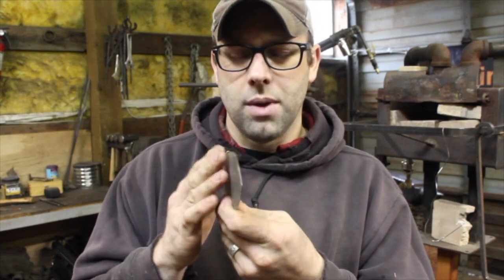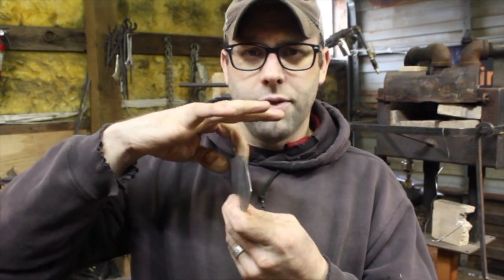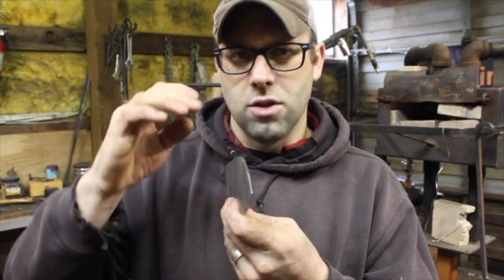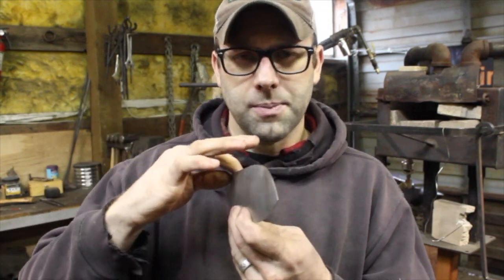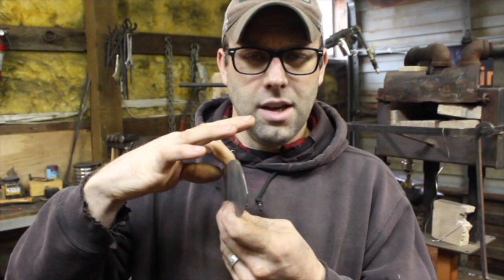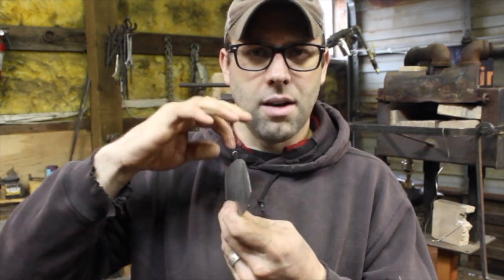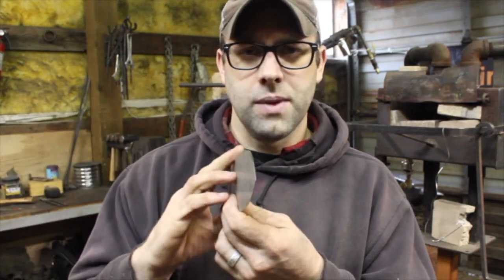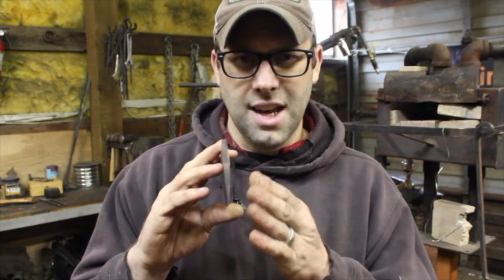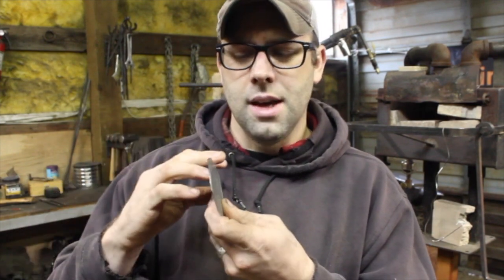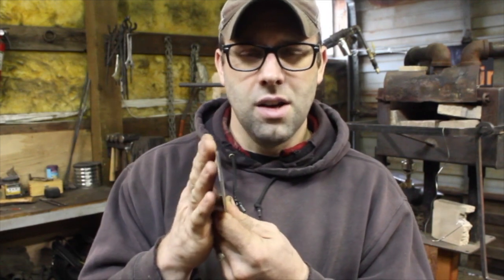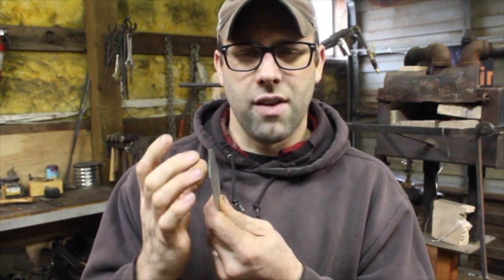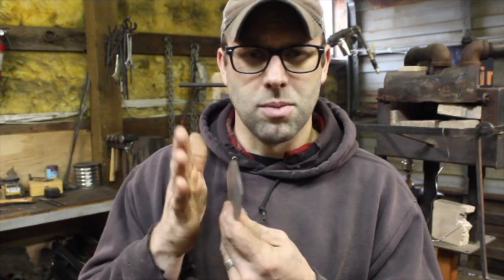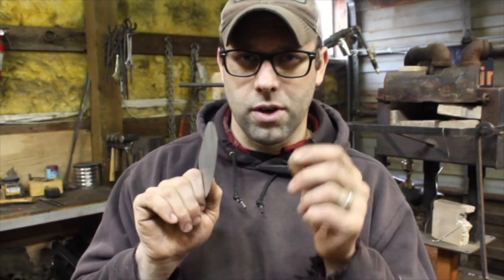straight. Oftentimes the opposite is true, and the reason is because after you've normalized, you've hardened, you've heat treated, and you've tempered, done the rough grind, etc., and you have a little kick to your blade, oftentimes that's because the material is not in a static state at that point. And so oftentimes what you need to do is remove material from the cupped side so that there is less tension on that side, and it allows the blade to move straight. Counterintuitive, but very, very useful.